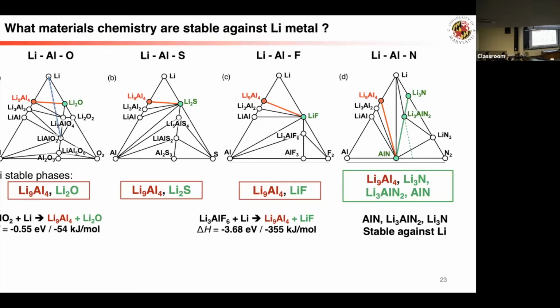Okay, people often think fluoride is more stable, a very stable material, right? But it's actually not necessarily. And what we find very interesting is that it's actually nitride, right? Some materials people know as a hard ceramic, and sometimes also used for coating in structural materials. But basically, they are thermodynamically stable with lithium, right? This lithium nitride and this aluminum nitride.